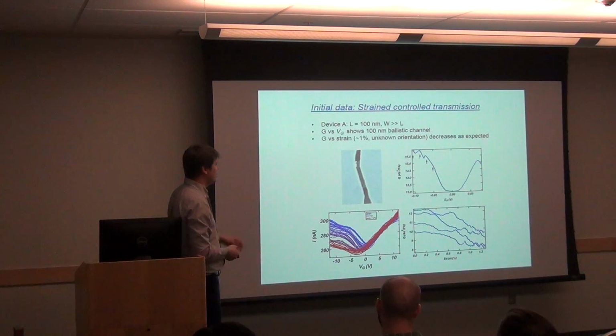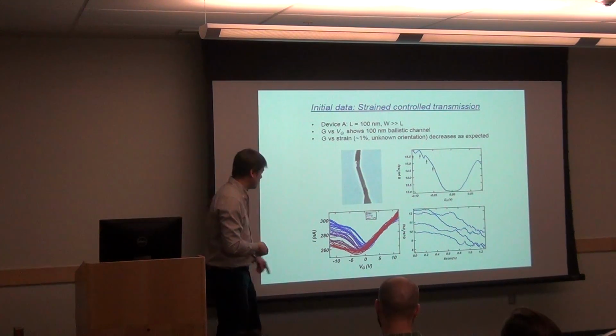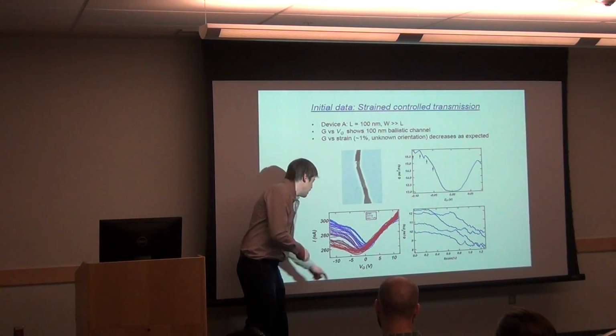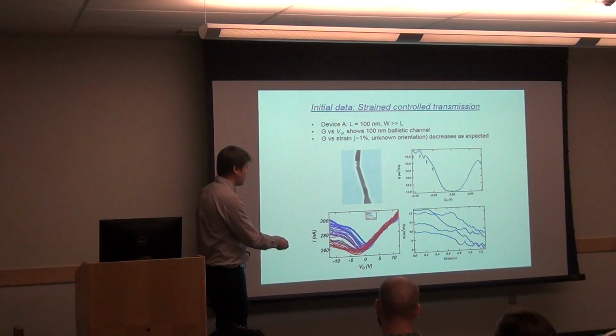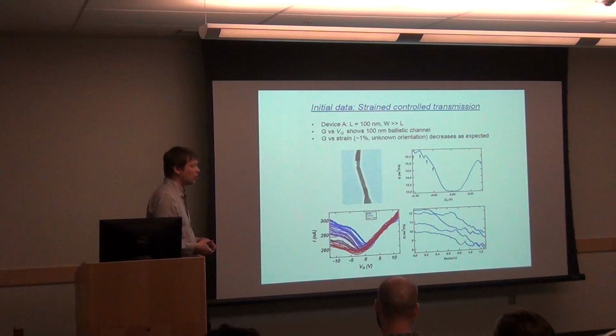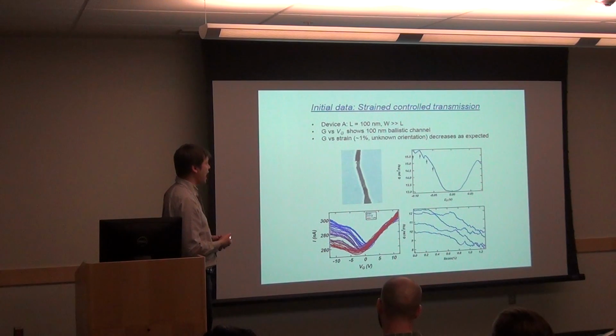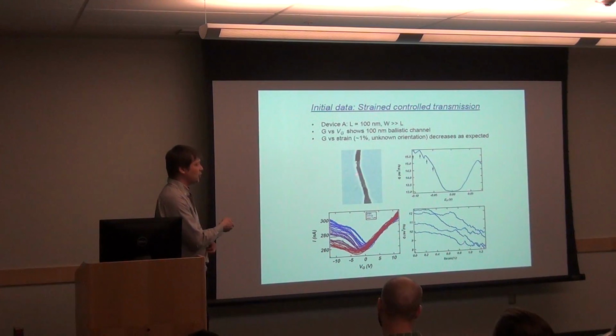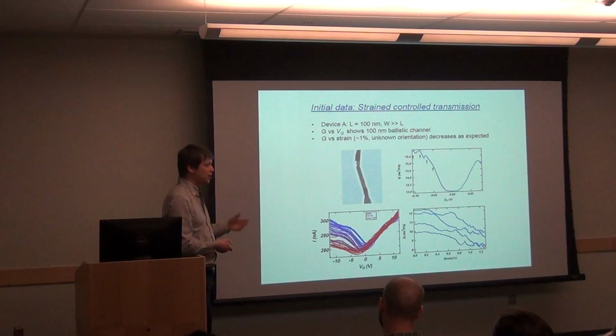Here's an example of initial data we have. This device wasn't perfect with its orientation, but it was pretty good. And we can see Fabry-Perot interferences again. Those told us that it's a ballistic device. And then if you apply the strain to it, you can see that current goes down, and also the Dirac point is shifting. Both of these things match qualitatively with the modeling that we have. In this case, we only applied about 1% strain because it was a 100 nanometer long flake. So that's why the effect is sort of modest, but that also matches with the modeling.